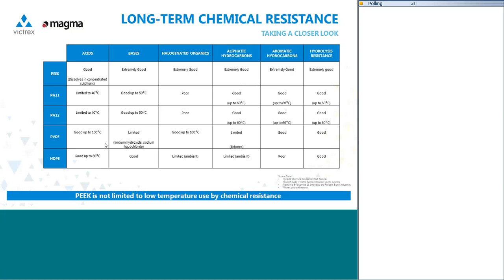So it retains that chemical resistance over a very wide range of temperature. As I say, these other materials all have fairly promising chemical resistance at room temperature, at ambient temperatures, but of course they are limited. I've taken this data from a number of sources which you can look at your leisure, but you'll see that, for example, the nylons, their chemical resistance is beginning to reach its limits when you get up to around 60 degrees centigrade.